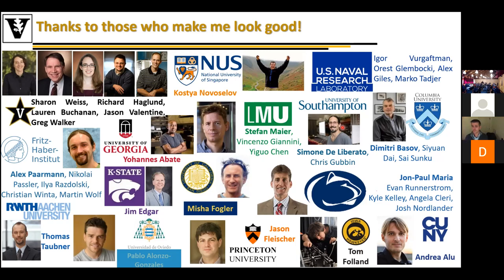And also, what is the smallest thickness you can get with this material? I'm sorry, I missed what you said. The thinner layers that you can get with these materials, I remember was around 1 micron. Depends on how much patience you have. We've gotten down to 200 nanometers. I've seen papers in the literature where it's usually in the order of a few hundred nanometers to a micron. I've seen a couple people talk about much thinner material down in the tens. We have not had success getting down there.